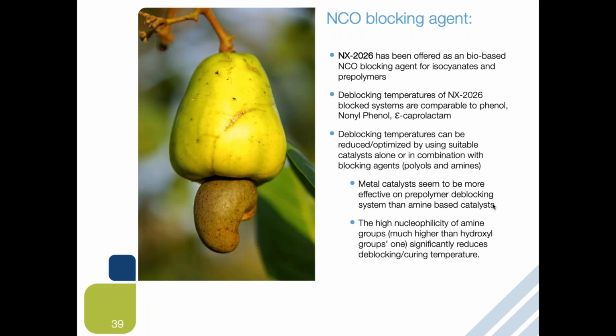So we have looked at NX2026 as a bio-based blocking agent for isocyanate and pre-polymer. We have seen so far NX2026 is comparable to phenol, nonylphenol, and caprolactam when it comes to blocking performance. At the same time, using NX2026 can offer you lower viscosity of your blocked system. We also noticed that, as with phenol and nonylphenol, the blocking temperature of NX2026 itself can still be high for some applications. Therefore, we have worked on options to optimize the deblocking temperature.